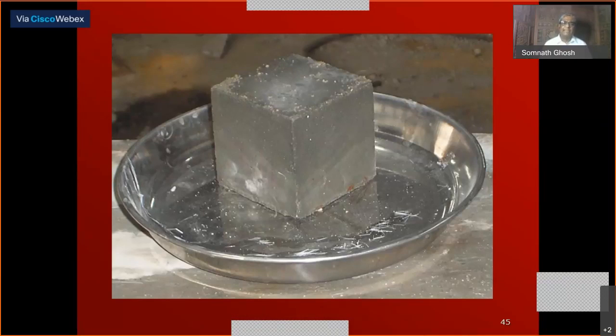Sometimes people are saying that if fiber is added, the finishing is not good. So that's why I thought I'll show you this piece of cube. Now you see, this is the kind of thing. Just observe the mix, right? And then the water powder ratio, then those of this normal superplasticizer, then viscosity modifier, and these are the V funnel results, slump flow results, and no bleeding. That is the most important thing. So even if we use fiber, if you can cook it properly with other ingredients, you will definitely get very good concrete. And similarly, other things also we have tried and we found not always good.